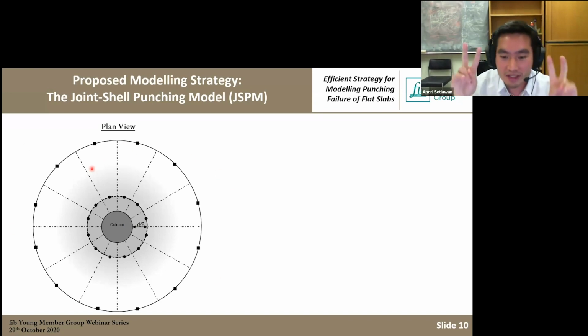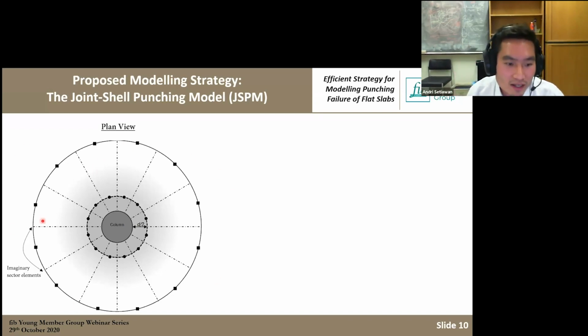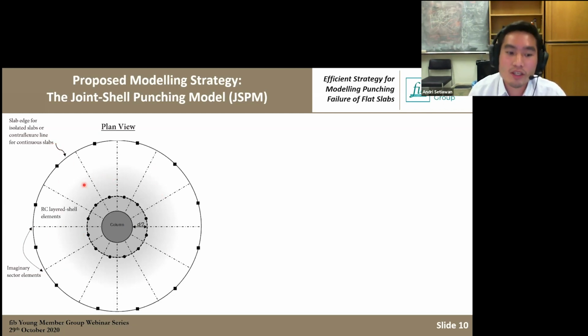We also imaginary cut the slabs into several sector elements, which can be seen here. We have imaginary sector elements, and the edge represents the slab edge for isolated slabs or contraflexure for continuous slabs. As I said before, we use shell elements to model the bending behavior. And then at a certain location close to the column, where we assume that the punching happens at half of the effective depth from the column, to be consistent with the critical shear crack theory, we put joint elements. So the joint elements will trigger the failure around this perimeter.